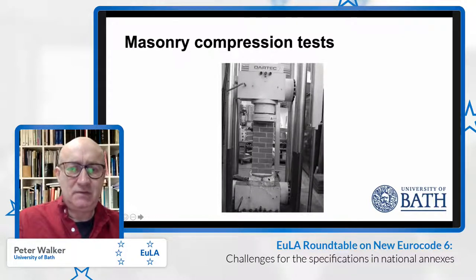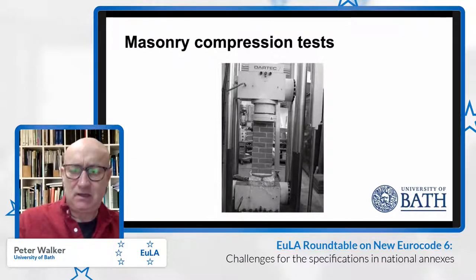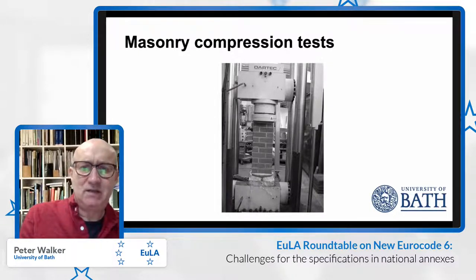You see 750 millimeters high. They're only 1.5 bricks or 330 millimeters wide. In part, they were the same dimensions as used for the creep tests, and the limited width of the test walls, compared with some other arrangements, was in part to make the loads that we needed to supply in the creep testing manageable. Obviously, as the width of this wall increased, the amount of load to maintain that stress would increase, and that did present challenges for the creep testing.